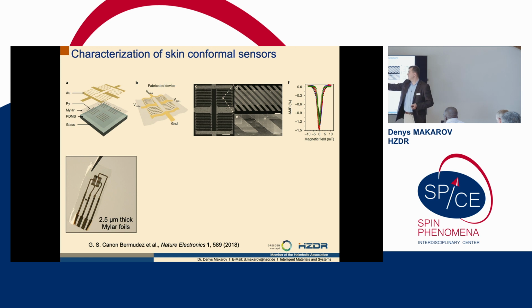So you start with a substrate, you put some anti-adhesion layer, usually you put something like rubber, which is synthetic rubber. Then you put the foil, which you want to use as a substrate. You do lithography, you do multi-step deposition, multi-step lithography. You define your layers of contacts, of sensors. You do liftoff, you do etching, whatever you want. And then you have basically a sensor of your choice. And what you do, you push current and you measure voltage. That's it, right? And this is like a typical curve, like anisotropic magnetoresistance, where you have a change of electrical resistance in the magnetic field. But you measure it now on something which is very, very thin. It's like, let's say, 1-2 micrometers thick.